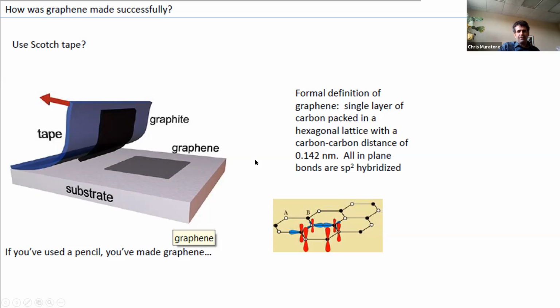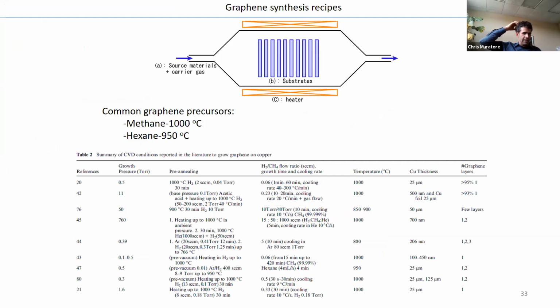This is the way that it was done, and this is a great way to make very small volumes of material for laboratory characterization. If you want to make larger samples and you want to use them for an application, a common way to make graphene is through chemical vapor deposition. And here's a bunch of different recipes for making graphene using chemical vapor deposition. This is just where you pass gaseous precursors over substrates that are heated, and through thermal decomposition of the gaseous precursors, you form a film on the surface.